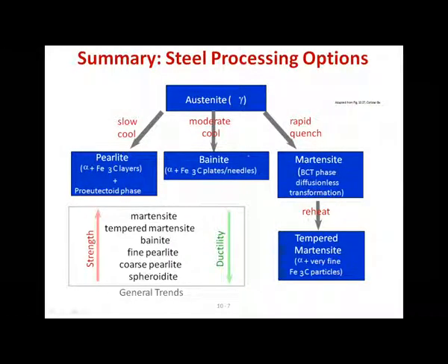Then, when I vary the cooling rate, the arrangement of those two phases in 3 dimensions, the microconstituent or the microstructure, we have a lot of ability to engineer that. So the complexity is part of what makes steel so great. And each of these, so composition, cooling path, microstructure, each of them is a different material with different material properties. So go ahead and look in the back of the text. For steels, it has a whole bunch of different kinds of steels, and it lists their mechanical properties: modulus, yield strength. And you can compare them.